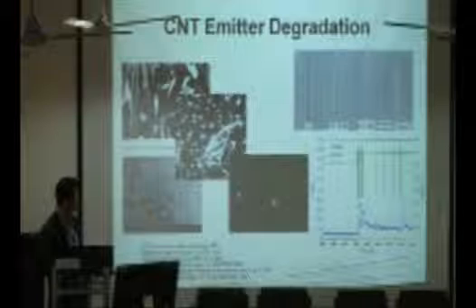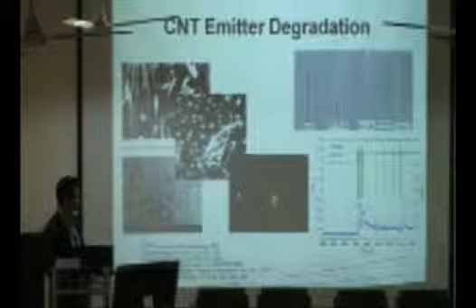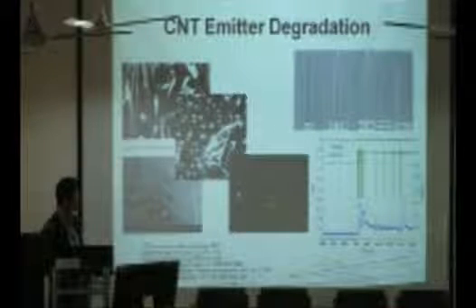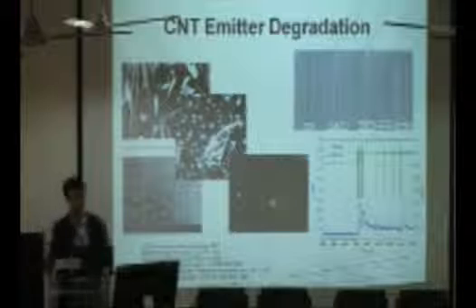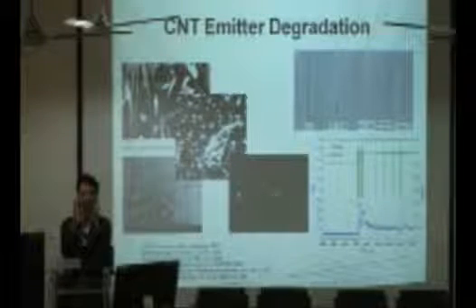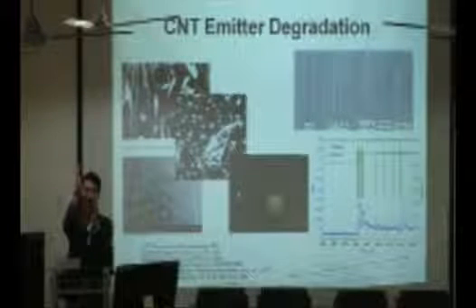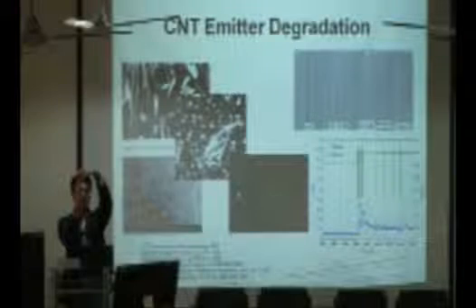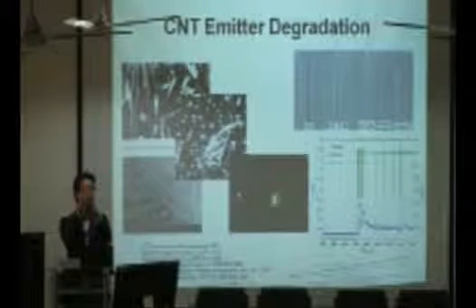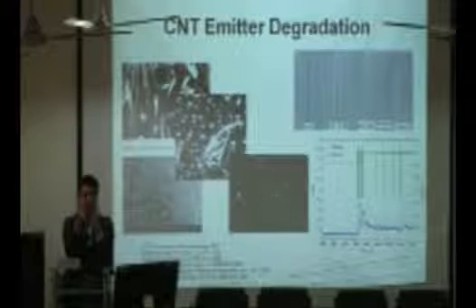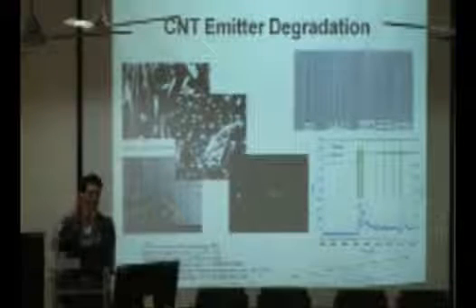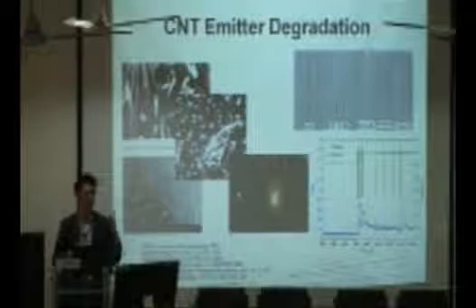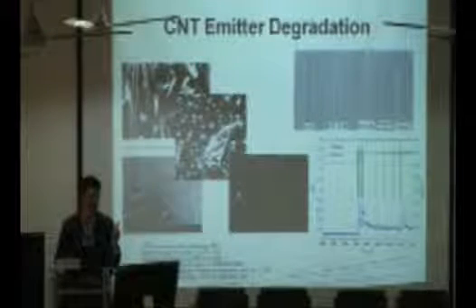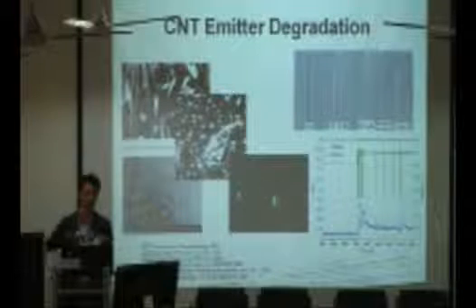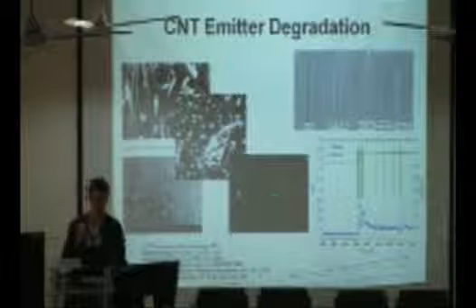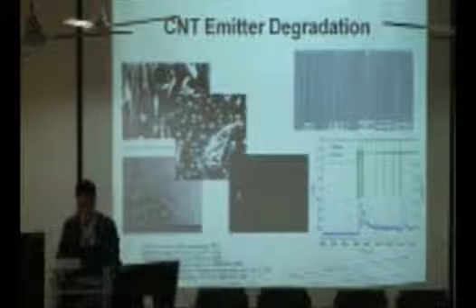This is a fluorescence experiment of an array of CNT. You see hot spots of current emitting CNTs, and you see cold spots as well. So what you're looking at here is certain CNT are taller than the other CNT. Because it's taller, it has a really high concentration of electric field. So this single strand of carbon nanotube emits more current. As this CNT burns off, you have a new CNT, which is taller, and it starts emitting current. So we are talking about non-uniformity of current intensity. We are also talking about non-uniformity of current emission across a 2D area. So these are the technical challenges that we have to address.